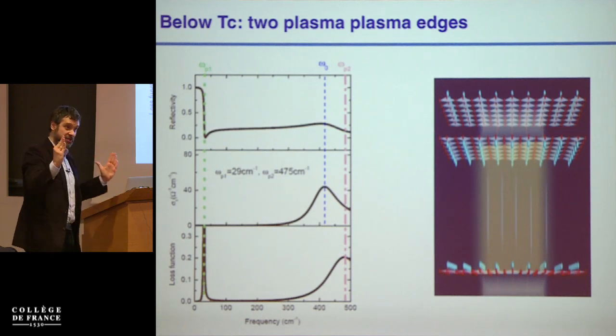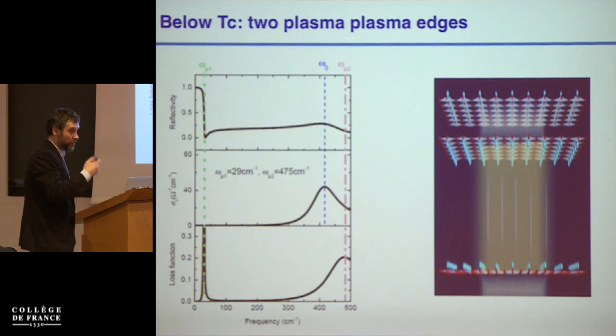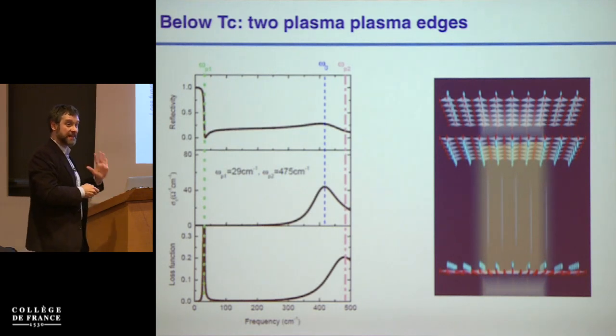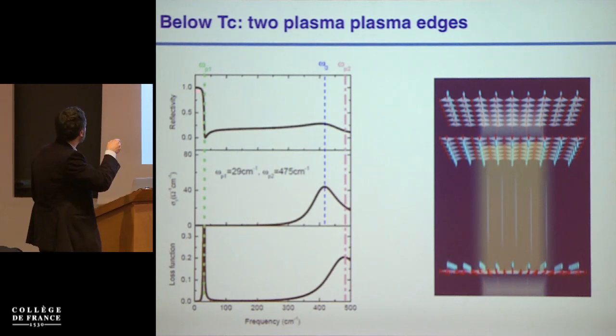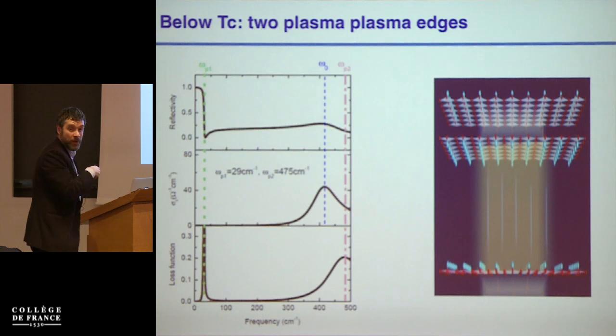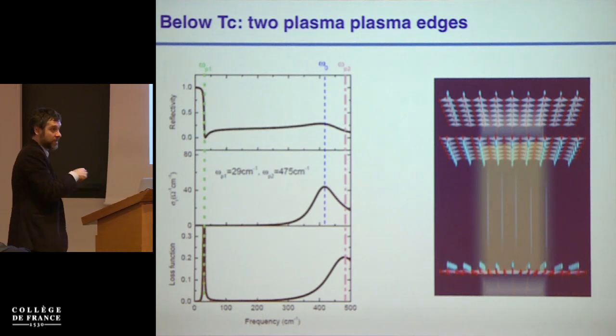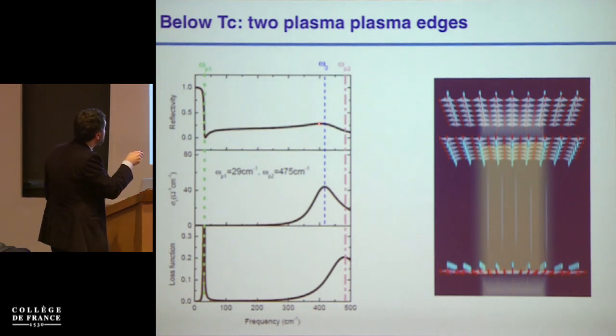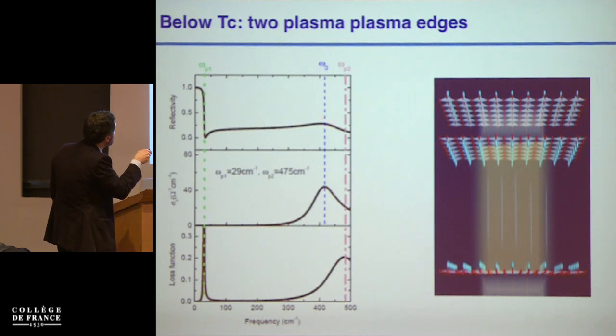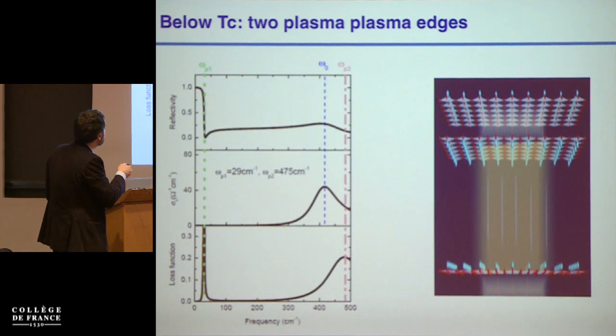This is a long Josephson junction with weak coupling, and so with an inductor that is large, and so with 1/LC that is a small number, and hence this would be related to this plasma resonance. This is a calculation, by the way, to a plasma resonance at low frequencies. This is the inverse of epsilon1. That tells me there's a zero crossing of epsilon1, and then I will have a second peak. A second edge you can kind of make up here for various reasons that I'm happy to discuss later.